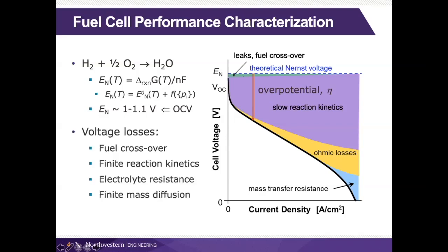And that's due to a number of things. Here I'm just showing a little bit of impact of fuel crossover. If your membrane were a little bit leaky, you have some finite reaction kinetics that causes the voltage to decrease because of these poor catalysis rates, some things that Tom hinted at. Then we start to see the impact of the electrode resistance, so a linear portion here, an ohmic contribution to the cell voltage drop. And then if we're trying to draw very large amounts of current out of our system, we might start to see some mass transfer resistance, which means that the gases can't get to the reaction sites as quickly as we'd like to pull them across.